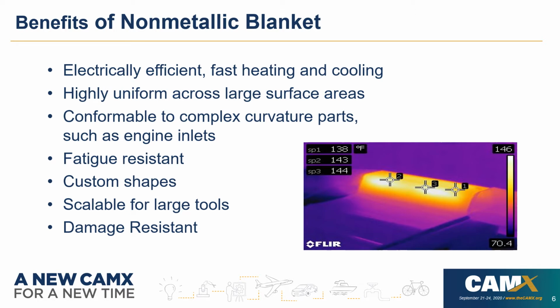The non-metallic nature of this product leads to fatigue resistance. We can mold it into custom shapes. Again, the continuous film is more scalable and conducive for larger tools or blankets. And because it has this continuous network of carbon conductors, it is more damage resistant. If the carbon conductor gets damaged, there's still an electrical pathway for this blanket to operate. Whereas if a metallic filament blanket were to work harden or break or short out, then that's a single point failure mode.